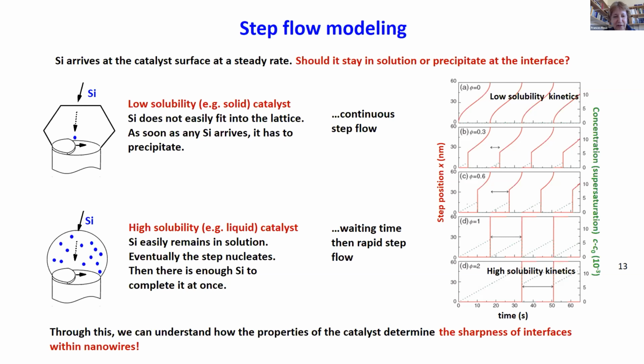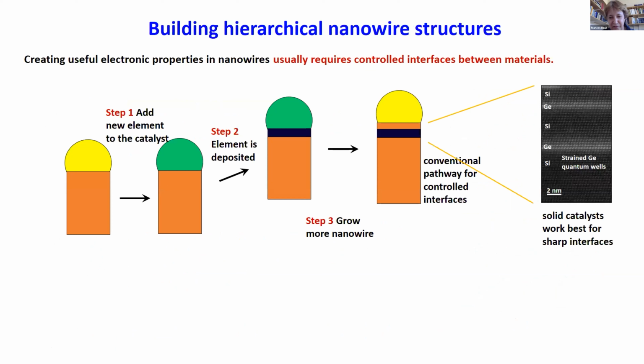So we can look at this and say, oh yeah, this will help us understand things like, how do I grow a junction in a nanowire? For example, I want to grow some silicon, and then I want to grow some germanium, and then I want to grow some more silicon. How sharp will that junction be? Well, you can guess that it's going to be a lot sharper in the first case than in the second case, because we have such a reservoir of the growth material. And indeed, this is the case. Depending on the catalyst properties, you get very different interface sharpness when you grow heterostructures.